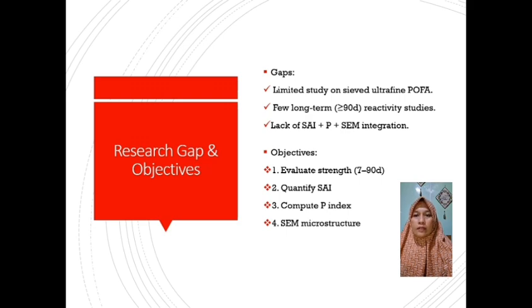The objectives of this study are to evaluate the compressive strength development of 10% and 20% POFA mortars, quantify the strength activity index according to ASTM C618, compute the pozzolanic contribution index, and examine microstructural morphology using SEM.